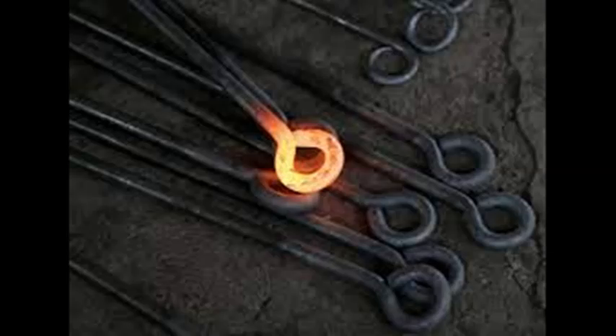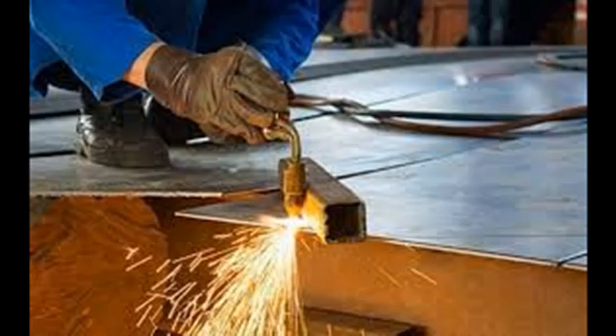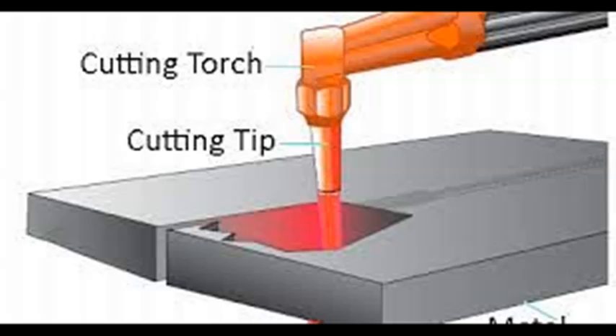After the plate has reached its ignition temperature, the operator should release the oxygen jet to start cutting and then move the torch in the forward direction to achieve the desired cut. In oxyacetylene gas cutting, forward cutting speed is very important to maintain properly. If the torch is moved very rapidly, the metal at the bottom does not get sufficient heat to get oxidized and cut, which causes a very rough and irregular cut.